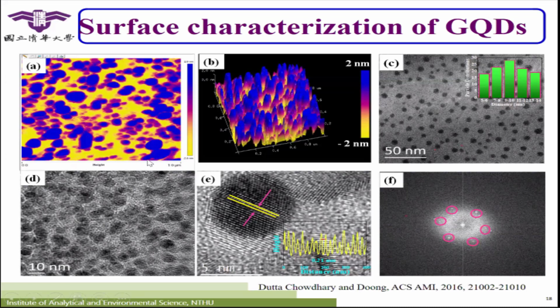When you see the blue colors, those are the graphene quantum dots. When you use the atomic force microscope to see the topography and measure the thickness of this carbon-based material, you can see their thickness is only around 2 nanometers. One layer of carbon is around 0.334 nanometers. Graphene oxide will be around 0.8 nanometer. So 2 nanometers means they only have a few layers of carbon. Since there are only a few layers, we can make sure it is graphene quantum dots and not carbon dots. On figure C, we see their particle size from the TEM, at around 9 nanometers. I don't want to go into detail.